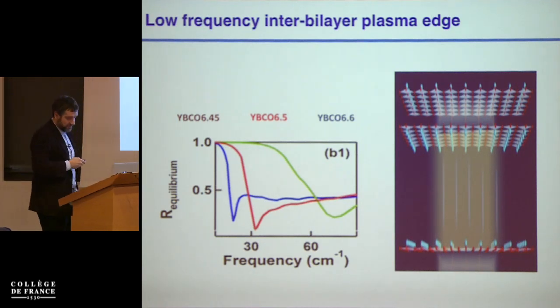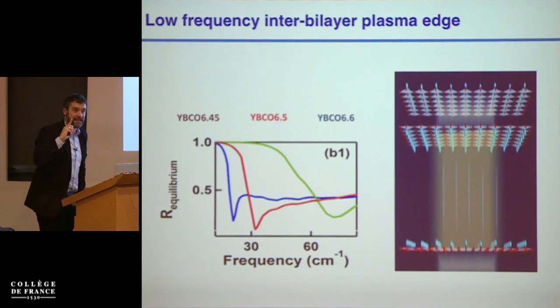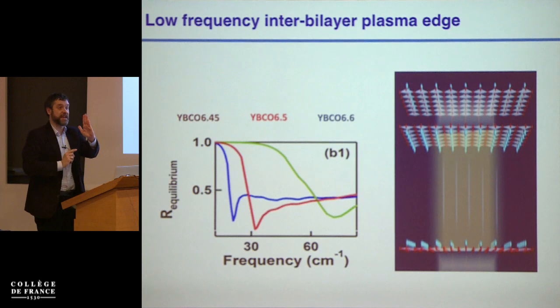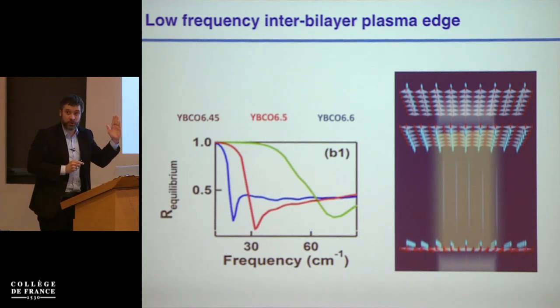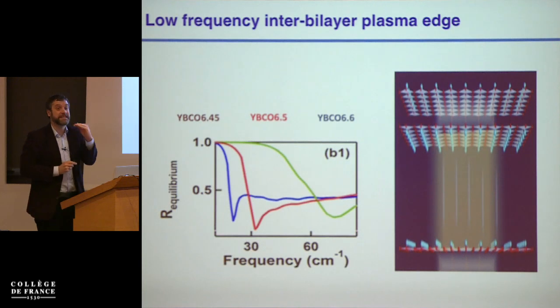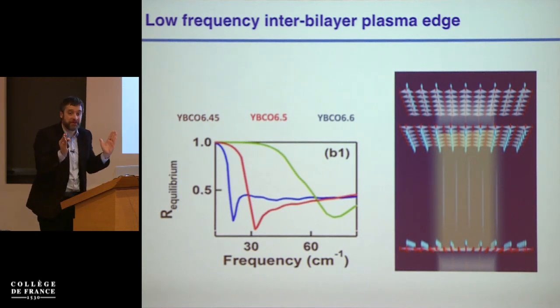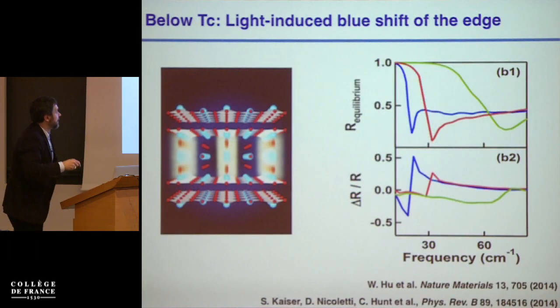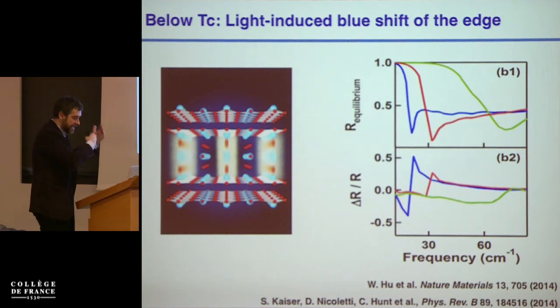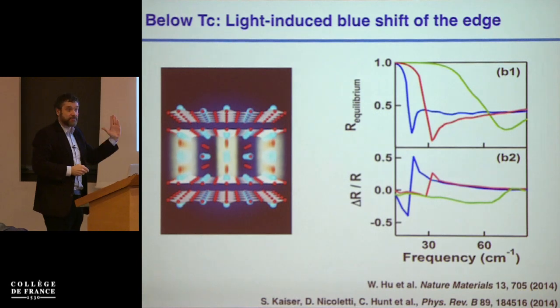Okay, and so the first thing we do is we go below TC and we excite the apical oxygen, and we look at this edge and we want to see whether the edge shifts to the red, meaning that I'm making superconductivity worse, or it shifts to the blue, which means I'm making at least the interlayer tunneling better. Okay? These are the differential measurements in reflectivity, and if you recalculate the whole thing, what you find is that there is a blue shift of all these three edges.